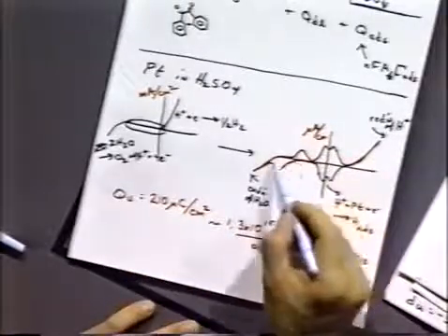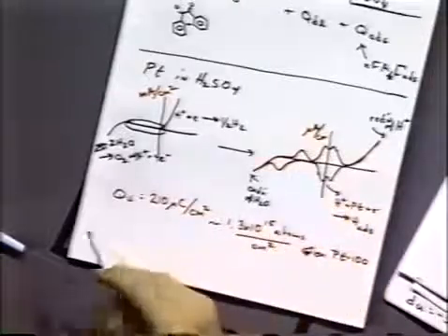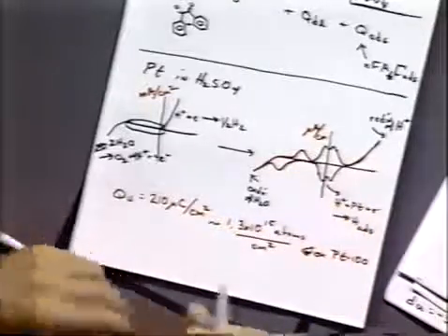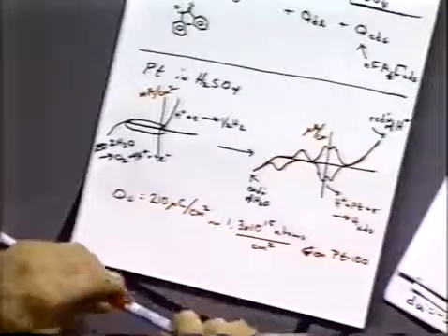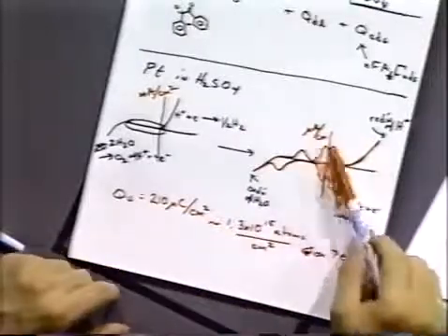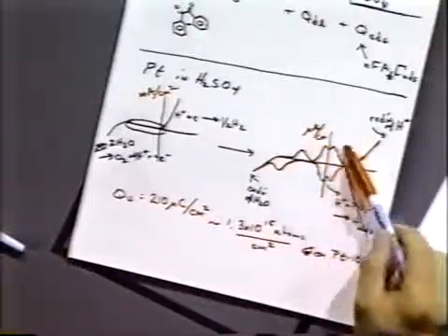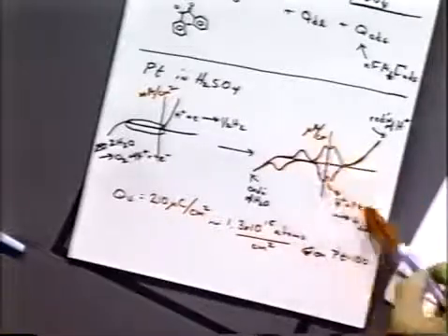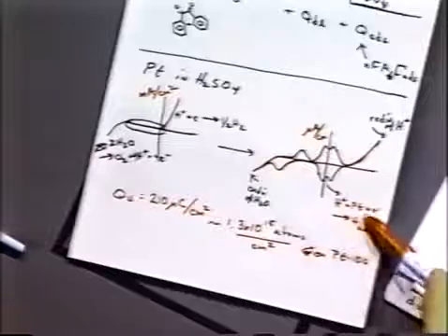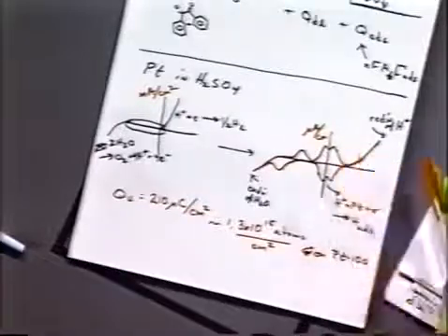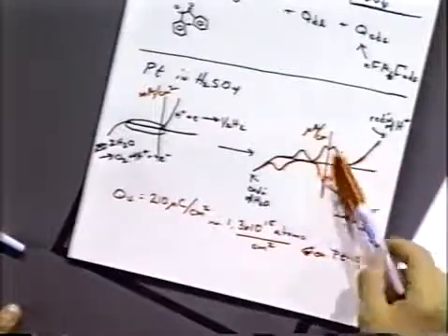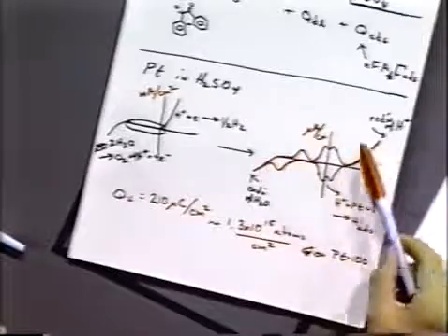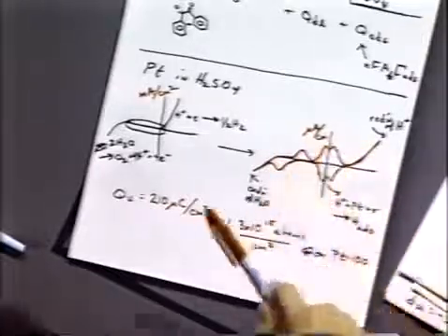And so you could also use this peak or this peak to get the electrode area as well. But usually they use the hydrogen peaks. So that's very diagnostic for platinum. Now for other materials like mercury, we don't see those peaks because we don't see adsorbed hydrogen atoms in mercury. Gold and palladium, we'll see peaks similar to these, although different in shape than these.